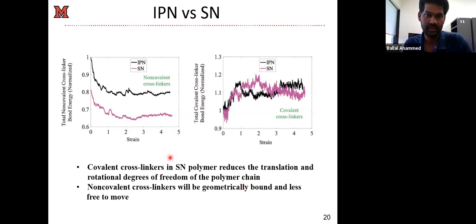As I mentioned previously, the difference between those two network structures comes from the cross-linking. In one case, we have just one type of crosslinker in one chain, but in the SN case, we have both types of crosslinker in one chain. Then we looked into the non-covalent crosslinker bond energy and the covalent crosslinker bond energy when you apply the strain. We see that for the non-covalent crosslinker bond energy, for the IPN case, the energy is always higher than the SN case. But the total covalent bond energy remains quite similar when you apply the strain in the material. That means it is the non-covalent crosslinker which is giving some extra advantage to the IPN materials.